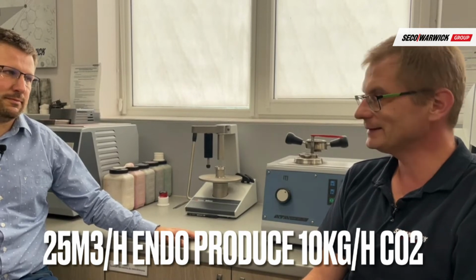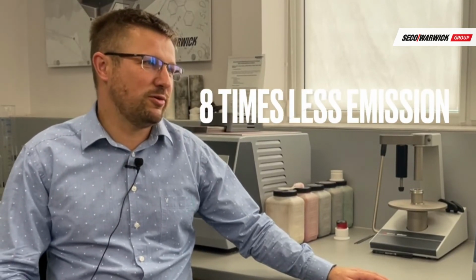Carburizing seems to be really easy to explain. Low pressure carburizing follows the ecological way. When we compare traditional carburizing with low pressure carburizing, we can clearly see the ecological trend. Did you know that 25 cubic meters per hour of endo atmosphere produce 10 kilograms per hour of CO2? It's roughly about 80 tons of CO2. We have the same trend in nitriding. As a good example, we can take zero flow technology, which also reduces emissions even up to 8 times compared to traditional two-gas nitriding. Yeah, zero means zero.